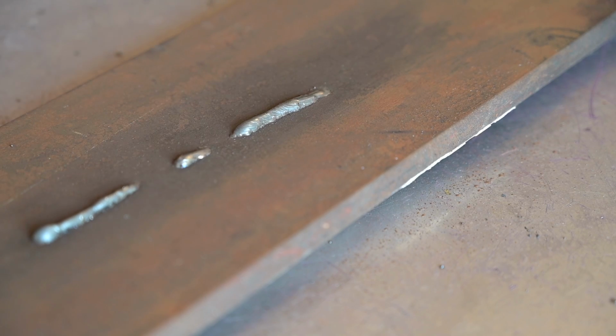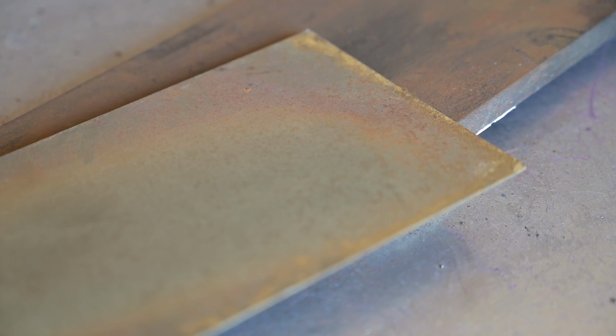And now I have a very nice weld. I just did a quick run, of course, on very thick metal, but the arc jumps very well over, so it starts very easily. So yeah, and the adjustments seem to be working quite well. I'm going to try this now on a thinner piece of metal. The thinner piece of metal now, this is about 0.8 mm. And then after that, we're going to try to put some pieces together. So let's see what this gives us.